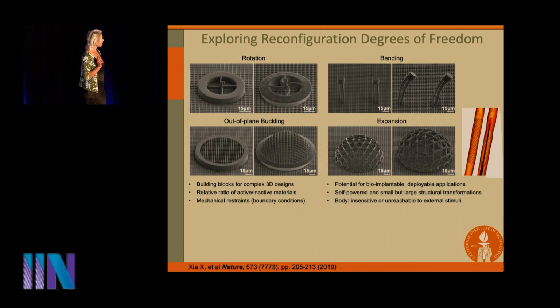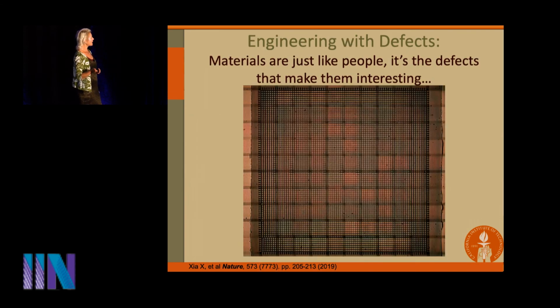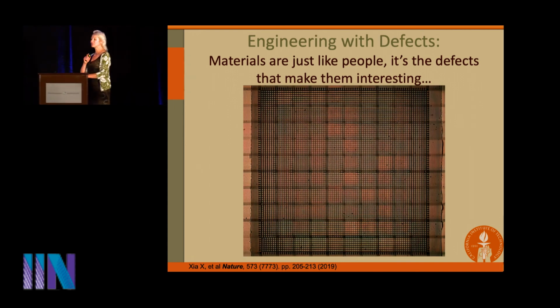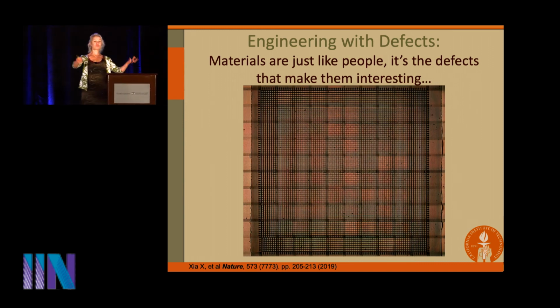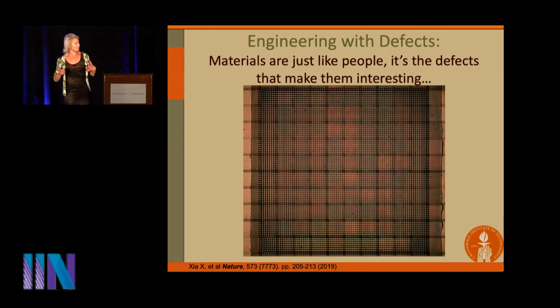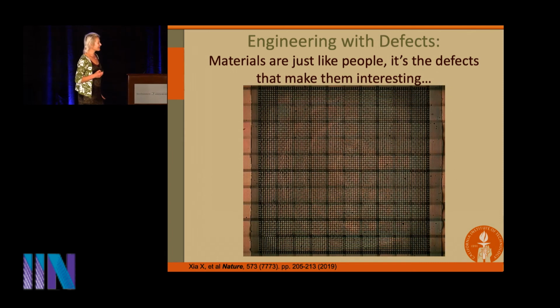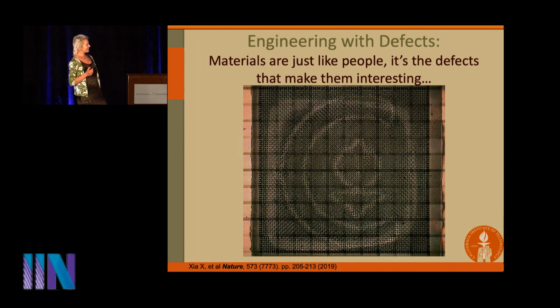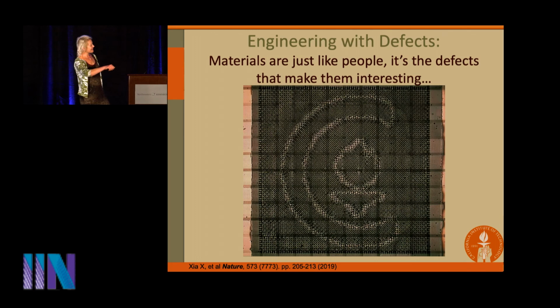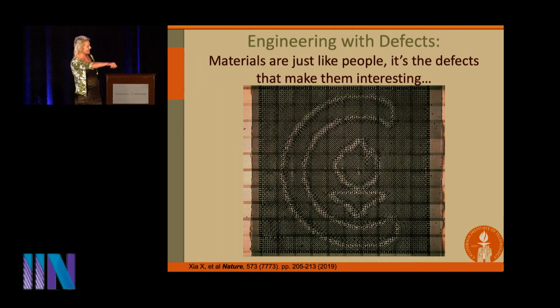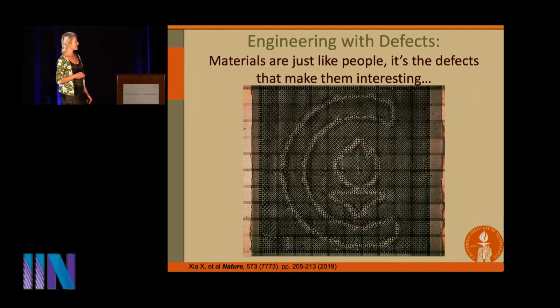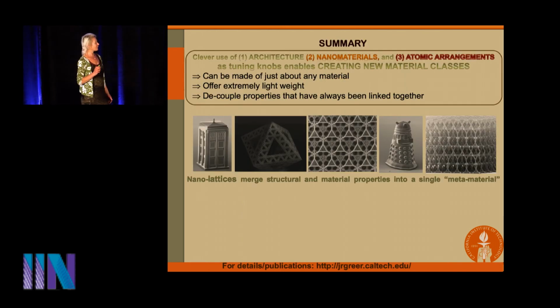What we'll learn more is that we have quite a few degrees of freedom. We can induce rotation, bending, buckling, and expansion. And here's the best part. Once we understood how these defects affected things like band diagrams, we can tame them and we can program with them. And so here's one of these microlattices, and we now programmed a pattern into it. And watch what happens upon lithiation. You don't know what it is, but now that we're lithiating it, you can hopefully see the amazing resemblance between what we programmed and my little Caltech logo down at the bottom. So once we understood the defects, we can actually put them to use.